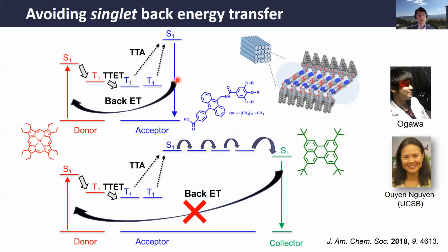Okay, so next I want to show you another example. Not only the triplet back energy transfer, but also the singlet back energy transfer is a severe issue in solid upconversion materials. This is collaboration work with Queen at UC Santa Barbara. When we use only donor and acceptor, the donor is PtOEP and the acceptor is this anthracene derivative. Actually, this forms a crystalline film by spin coating. By spin coating this donor-acceptor mixture, we observe severe back energy transfer, but by just adding this collector, we found that back energy transfer can be avoided.